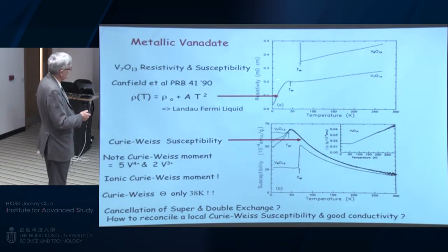Well, this one, which is metallic, this was the more recent work done by Paul Canfield. If you look at the resistivity and the susceptibility of this material, it's rather a curious metal with an almost Curie-Weiss-like susceptibility, very unusual for a metal, showing that there is basically sluggish motion of the electrons moving these 4+ and 3+ around. But suddenly when the magnetic ordering sets in, we get a nice T-squared law here, but no superconductivity. And so this low temperature phase here doesn't show superconductivity.